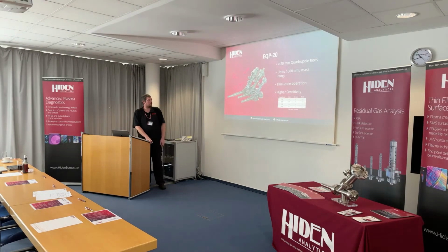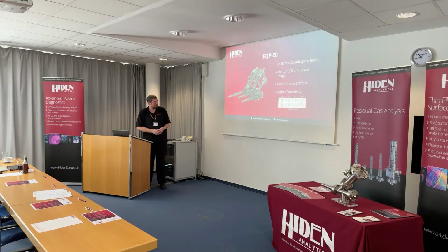Okay. So the next thing I want to talk about is the EQP20. It's called the EQP20 because it's got 20 millimeter quadrupole rods. So the 3 EQP members of the family are shown: the EQP6, the EQP9, and now the EQP20. The advantage of going larger with the quadrupole is it improves the transmission through it, so that gives us higher sensitivity. In the table, the important one is the ratio. At the low masses, it could be up to 16 times as sensitive as the 9 millimeter. That advantage does drop off at higher masses, but still up to 5 times the sensitivity. Because it's larger and it's harder to drive, the mass range is slightly limited compared to the other one, so it's only a maximum of 1,000.